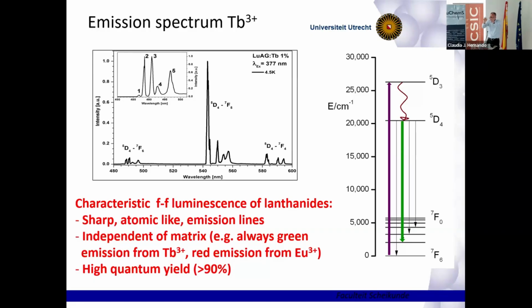This transition takes place in this inner 4f shell that is shielded from the environment by the 5s and the 5p. So those transitions have very weak coupling with the environment. So you get atomic-like sharp zero phonon lines. And that is really unique for the lanthanides and very profitable for many applications. Another special thing is that it's independent of the matrix. If you have terbium dissolved in water, or you have terbium in an oxide host, or you have terbium in a fluoride host, doesn't matter. This energy level scheme is always the same.